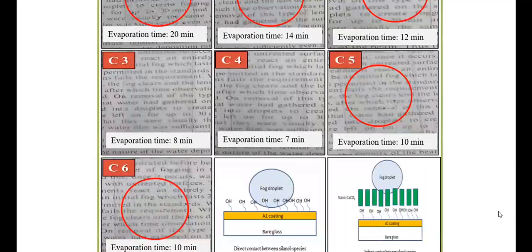So on the anti-fog properties, just now with only the binder system we see that about 12 minutes is the best, but over here the condensation of water vapor on the glass becomes lesser with lesser time. Evaporation of the water vapors is lesser time with nano calcium carbonate particles. This is why we are introducing nano calcium carbonate particles, because it creates air pockets. It's confirmed it is creating air pockets so that it does not adhere to the glass and can be easily removed from the surface.